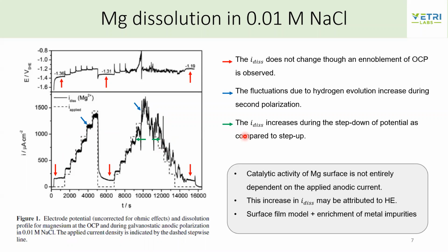They also found that the dissolution current during the slope, the negative slope of this particular curve, was very high as compared to the dissolution current that they saw here. As I will summarize in my conclusion slide, what they tend to say is that this whole phenomenon they attribute to two different factors: the instability of the passive film plus the enrichment of the metal impurities at the surface.